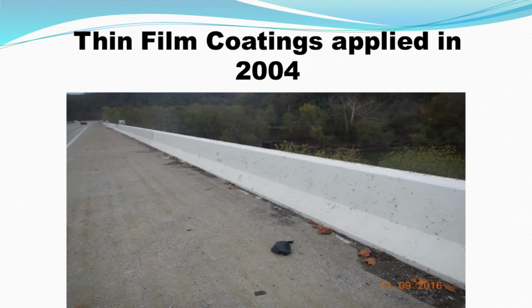This is a barrier wall that was an original field trial of a number of concrete coating systems. Some parts of the wall were pressure washed, others were abrasive blasted and had multiple coating systems put on them back in 2004. One of those coating systems was the same system that was used in the latest study, the 2016 study. And so it was an epoxy and urethane system. So there's a couple of different data sets that go to that particular system that has shown good performance, a good track record over time.